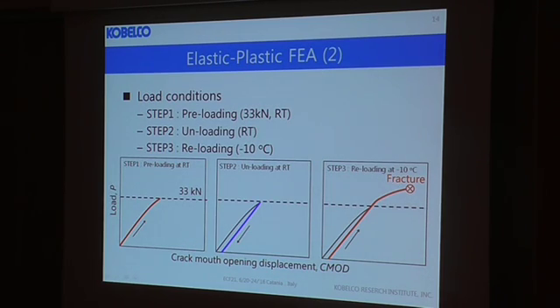Load conditions are summarized on this page. First, preload was increased to 33 kN at room temperature. Then after preload was unloaded, the temperature was changed to -10 centigrade. And then load was increased to the value of predicted fracture load. Material parameters were used as the properties for the temperature of each process.